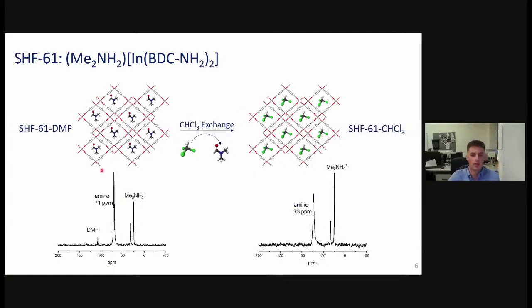So the framework's initially synthesized in DMF. What's nice about this is we can grow single crystals of it relatively easily, and that means we can characterize it through single crystal diffraction. Crystallographically, we see residual DMF from the synthesis residing in the pores of the framework. But we're able to swap that out for a more volatile solvent such as chloroform, and we're able to do this while maintaining crystallinity. Again, we see this full conversion of the DMF to chloroform crystallographically.